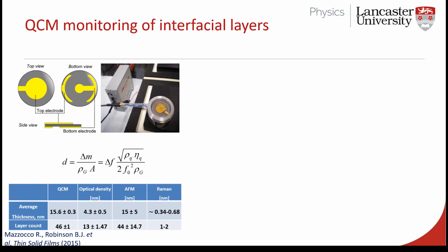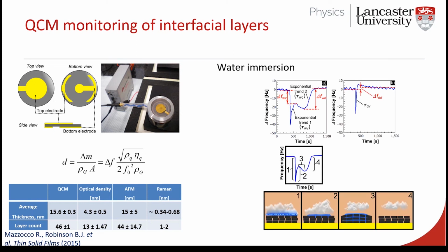So we can do interesting things like measuring the thickness of materials. We know how much mass is on there, we know how big the electrodes are, we know how thick it is. If you're packing materials on the surface, we can tell about their tilt angle. So we can get lots of very quick, very precise information about how we're modifying our surfaces. And we can tell how they're behaving, how they're interacting with the outside world. So in this case, this was a two-dimensional, graphene-based material that was designed to interact with, well, the application was underwater.